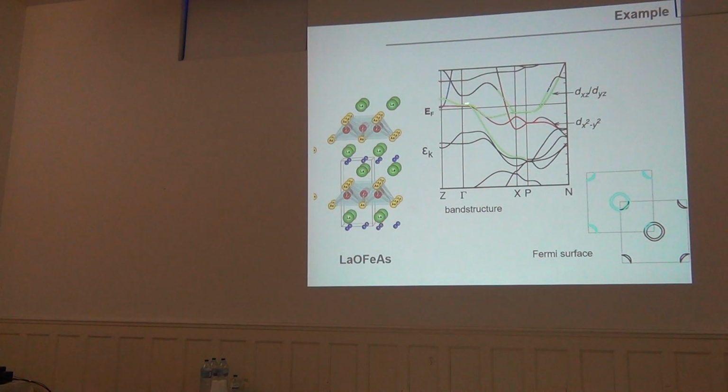And you see that basically near the Fermi level, which is what I am interested in because I want transport properties, there is no dispersion. It's a flat band. In a flat band, it means basically there is no dispersion of the electron, and this is what I would expect, because along this direction there is not much movement of the electrons. The electrons are mostly in these two-dimensional planes here, okay? Because these are mostly d bands, iron d and arsenic. The bands of lanthanum and oxygen are all filled or empty. They don't play a role except for charge transfer.